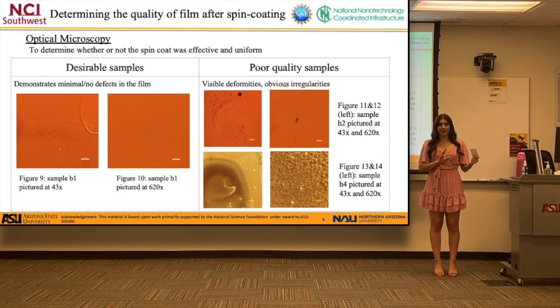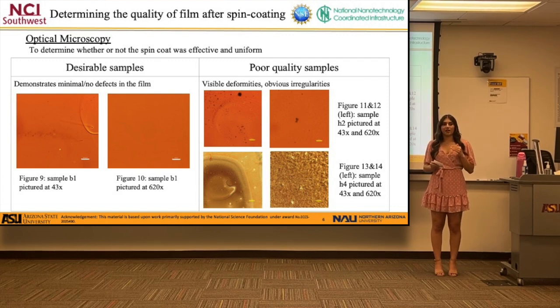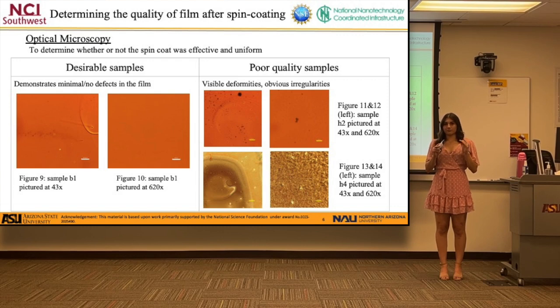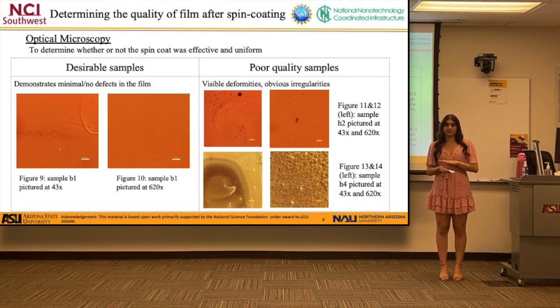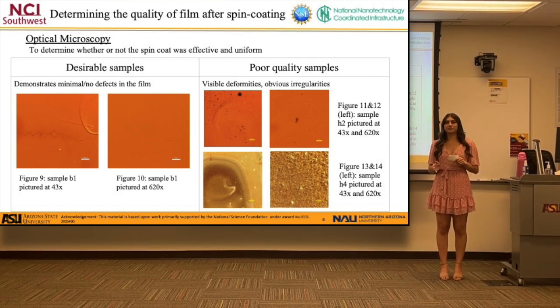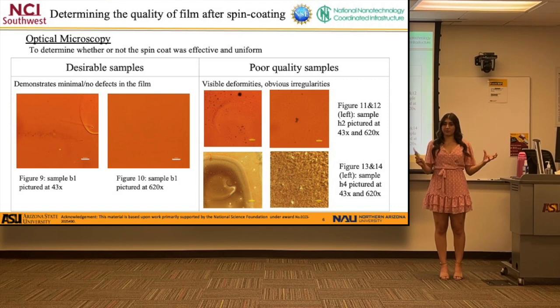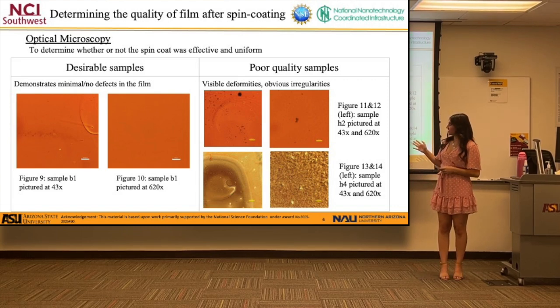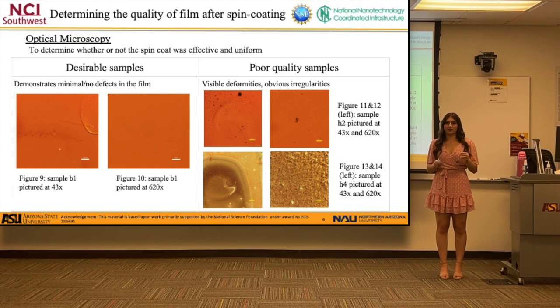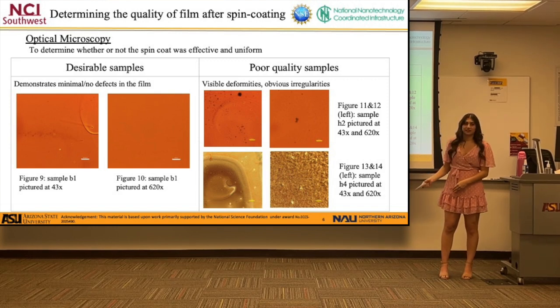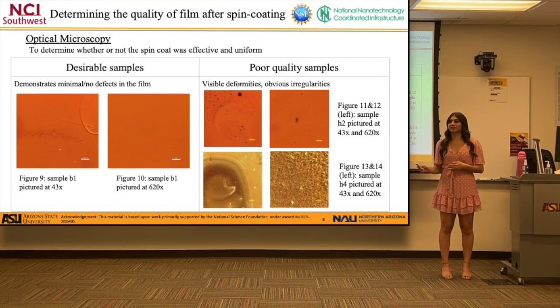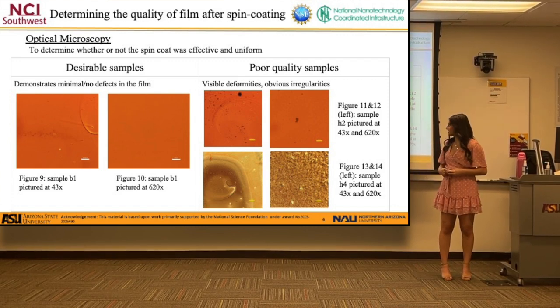After fabricating the device using the spin coater, we wanted to determine the quality of the film. So we used an optical microscope, and this is just a visual confirmation that our film is uniform. So as you can see, there's desirable samples, which is shown in figure 9. There's little to no defects, there's no holes, and there's no places where you would assume it would not be conductive. And there's poor quality samples, which you can see in figures 11, 12, 13, and 14, where there are visual deformities and irregularities, and this would lead us to think that maybe this device won't be effective during electrical and ionic testing.